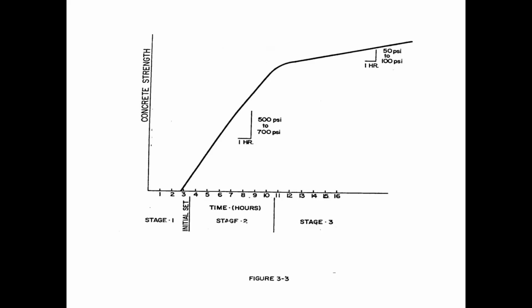This is a period of 8 to 10 hours over which the concrete increases in strength at a pretty significant rate. 500 to 700 psi per hour is not uncommon, or even higher than 700 psi per hour. After stage 2, we go into stage 3, which is a period where the concrete is still gaining strength, but at a much slower rate, generally in the 50 to 100 psi per hour strength gain range.